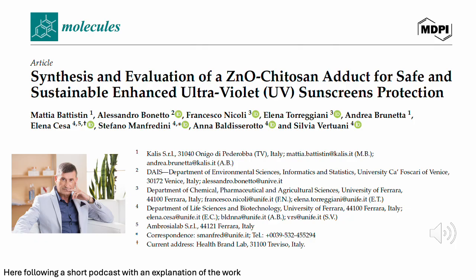Okay. And they tested this on a type of mouse skin cell. Essentially, they exposed the cells to different concentrations of either plain zinc oxide or ZnO@CS, and then measured how healthy the cells were afterward. So how did they stack up? Well, the ZnO@CS was significantly less toxic to the cells compared to the plain zinc oxide. This was especially true at higher concentrations. Yeah, that's great. So safer for our cells.